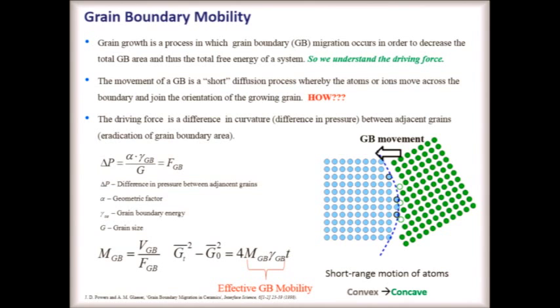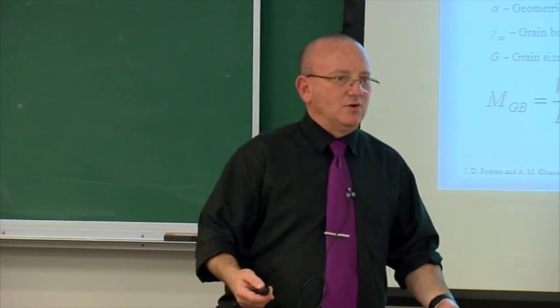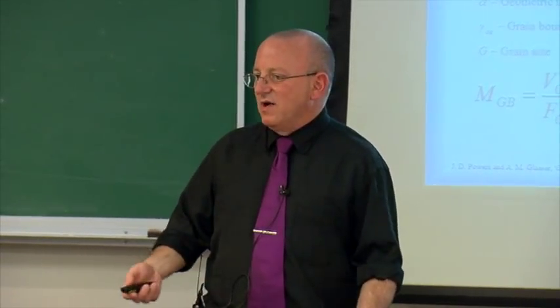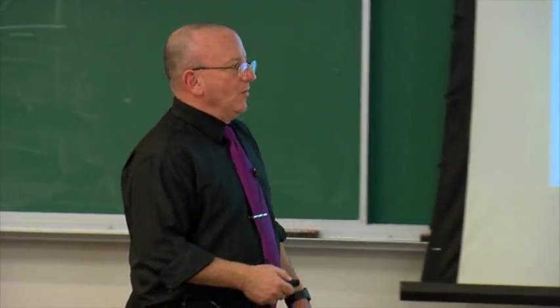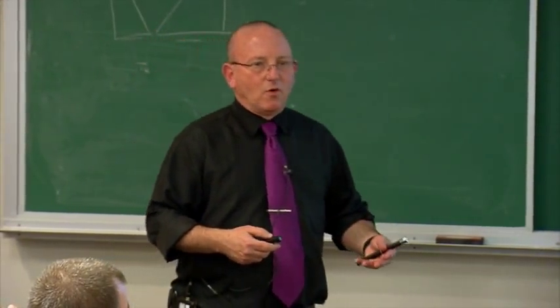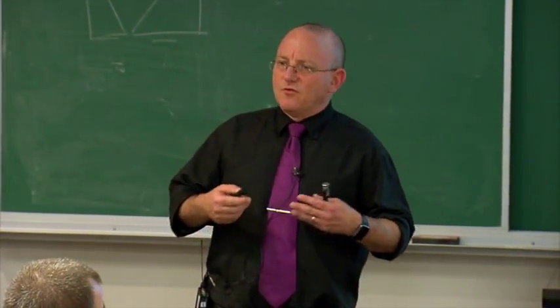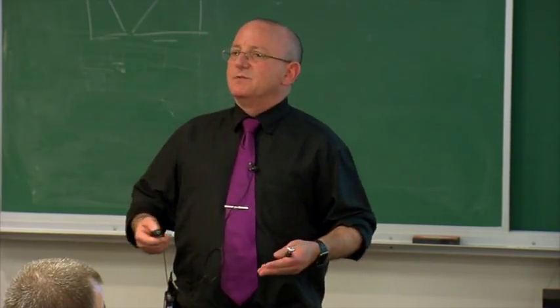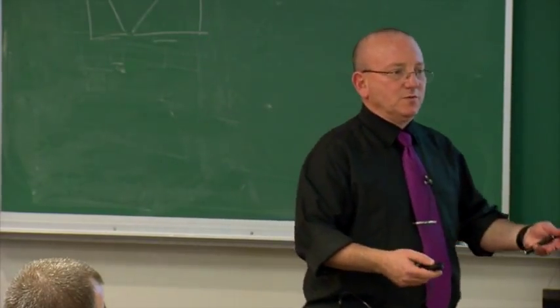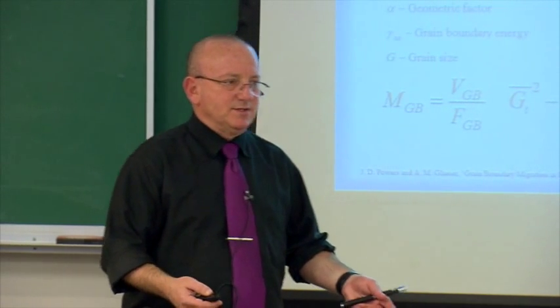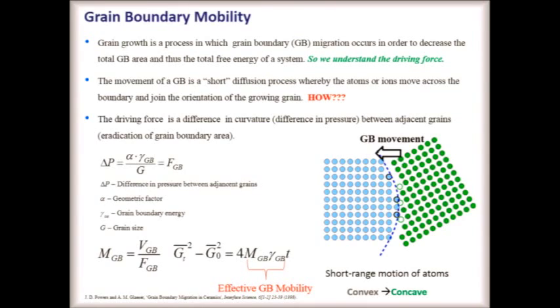Just to remind everybody, we can measure grain growth, and we know that the grains will get larger if we anneal things, but that's not a very quantitative approach. What we need to do is to look at the driving force, or look at the velocity of grain boundary motion and normalize it by the driving force, kind of like how we take a force, we normalize it by the area and define a stress. So that's the mobility, where we're taking the velocity divided by the driving force for grain boundary motion. And in the simplistic case, the driving force is the eradication of grain boundary area.